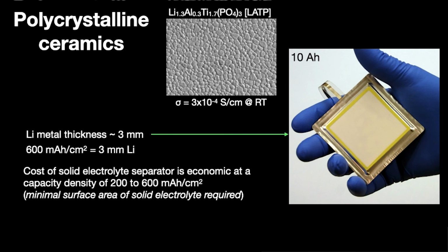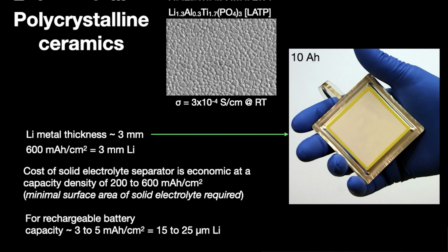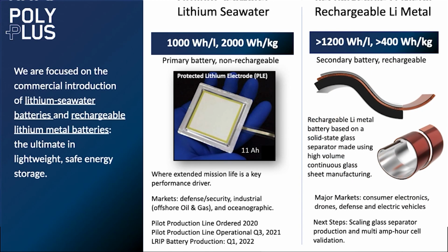If we're going to take that to a rechargeable, the metrics change, the cost changes, but at this capacity density, the cost of the solid electrolyte is fine, right? It's economic in this range. It will change if we start talking about rechargeables. So this is still the most expensive component of the lithium seawater battery. And the lithium seawater battery, as I mentioned, allows us to do some remarkable things, which is to build batteries at 2,000 watt-hour per kilogram, 1,000 watt-hour per liter. Polyplus now has a pilot manufacturing line in Berkeley. We're about to launch this commercially. And we just completed deep water testing. We had our batteries at 13,000 feet in the ocean, very high pressure, but these are incompressible electrodes, and so they do not need to be protected from those high pressures. So we can do some pretty remarkable things there with the solid electrolyte-based chemistry.